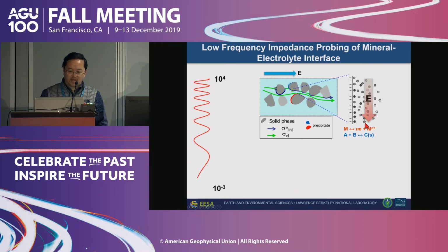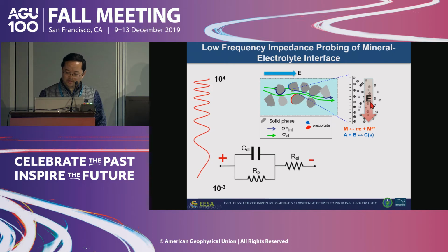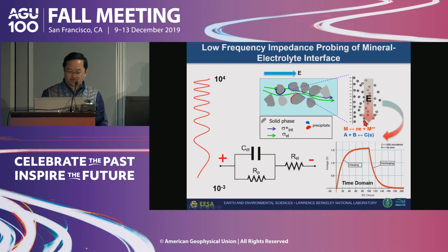When you apply a low frequency EM wave, you basically perturb this interface. The charge in the electrical double layer reacts to this low frequency energy, which can be used as a probing tool to look at the properties of the interface. Typically, people treat the interfacial behavior as an analog circuit model, where you have both a conduction component and a capacitive component related to the electrical double layer. This can be measured in either the time domain or the frequency domain.